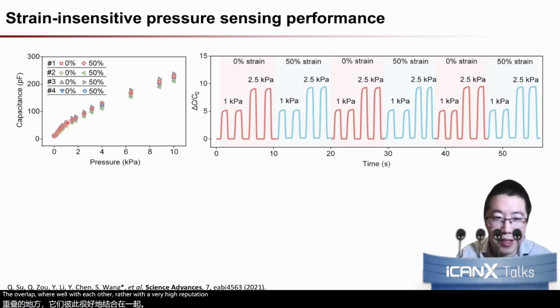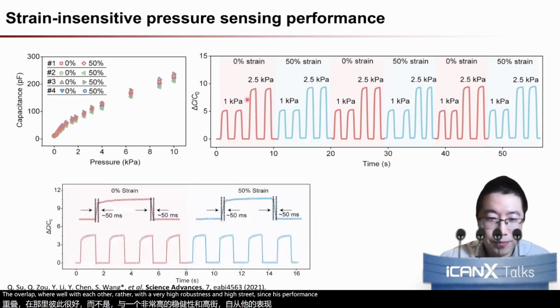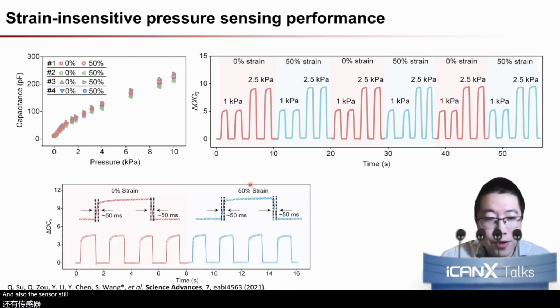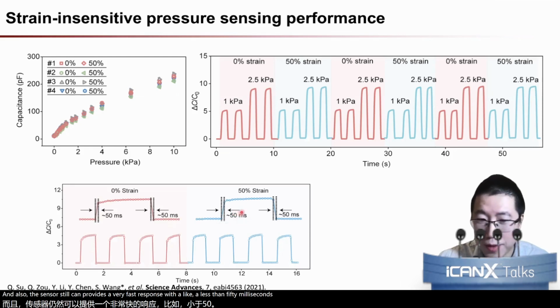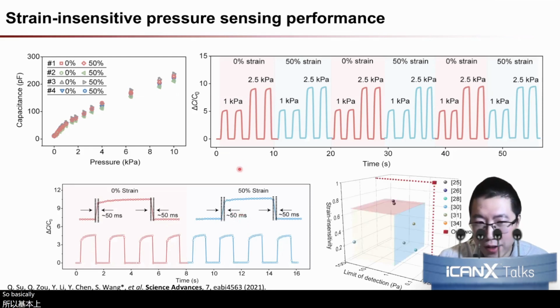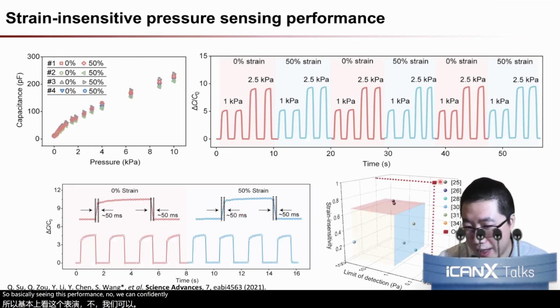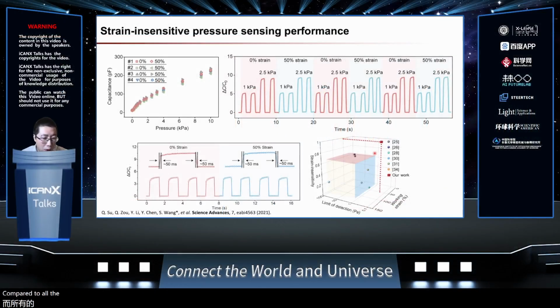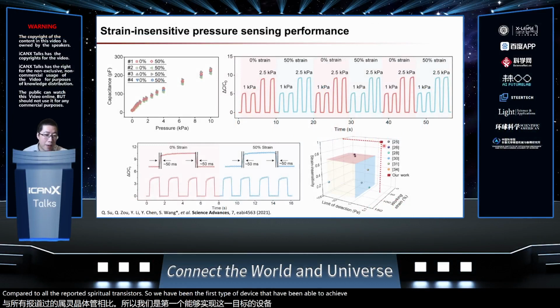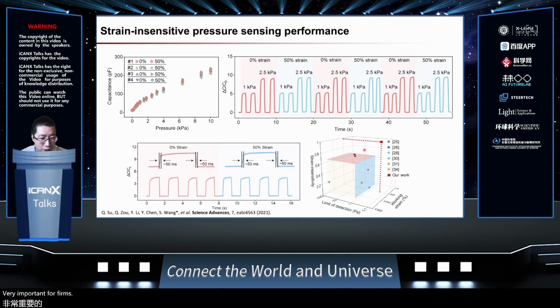With a very high robustness and a high strain insensitive performance. And also the sensor can still provide a very fast response, with a response time of less than 50 milliseconds. So basically, seeing this performance, now we can confidently say that compared to all the reported stretchable transistors, we have been the first type of device able to achieve the combination of three very important performance metrics, including the sensitivity, as shown by the limit of detection, the stretchability, as shown by the working strain, and also the high strain insensitivity.